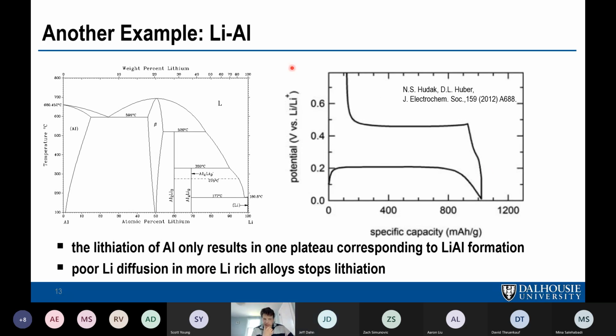Another example when you won't see a phase is because of kinetics. So lithium aluminum is an interesting system because according to the phase diagram, you should get almost 70 atomic percent lithium into aluminum. But in reality, at room temperature, you only get 50%. You only form the LiAl phase. And that's because these phases have very poor lithium diffusion. So when you lithiate aluminum, you form LiAl, and then when you try to go beyond there, you form a little bit of these phases, and it essentially forms a coating on the outside of the particles that blocks the insertion of more lithium. And you can see a little plateau here from delithiating these surface phases on the particles. So this is another reason why you might not see all the phases in a phase diagram: kinetic inhibition of forming that phase.